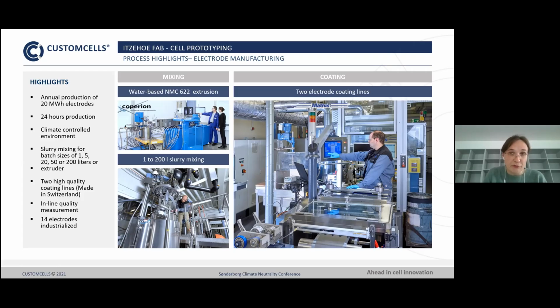It should not be too fast, or you will have inhomogeneity. So the good mixing that you have done in the step before will probably be inhomogeneous after that if you do that too fast, because the binder can migrate to the top of the layer, or if it's too slow, then it will just not be dry. And because this is a roll-to-roll process, then this would be quite messy. So it has to be done in the right way.